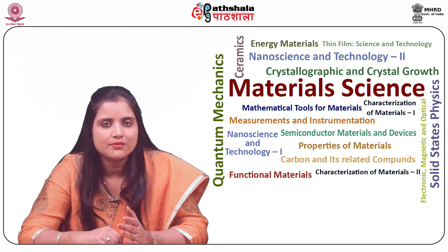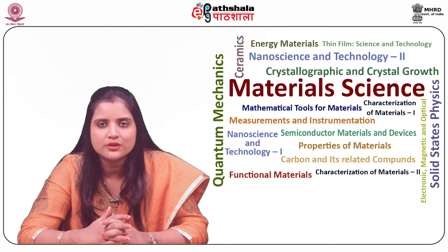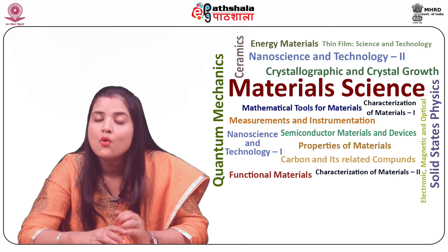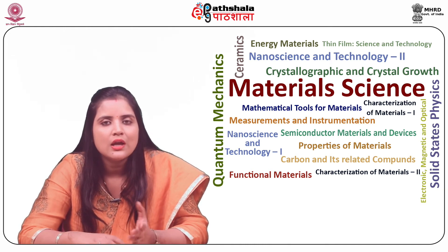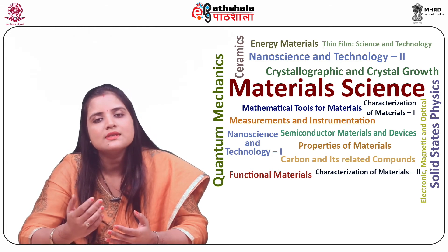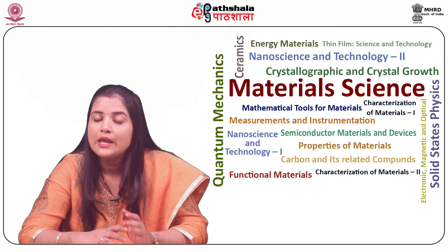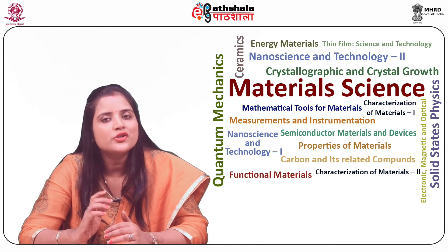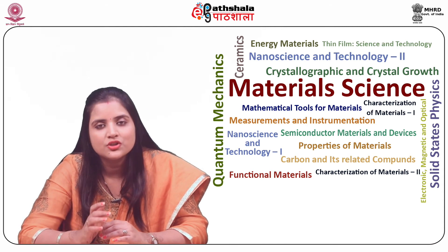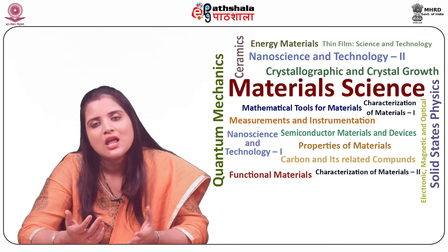Next, we will discuss about slits. Very flexible slits are used at the entrance and exit points of the monochromator. The band pass of the incident light is determined by the slit width on the excitation monochromator, whereas the fluorescence intensity signal is controlled by the emission monochromator slits. When setting slit width, the trade-off is intensity of signal versus spectral resolution. A wider slit width decreases resolution as extra light falls on the sample and the detector, whereas narrower slits provide higher resolution but at the cost of signal intensity.